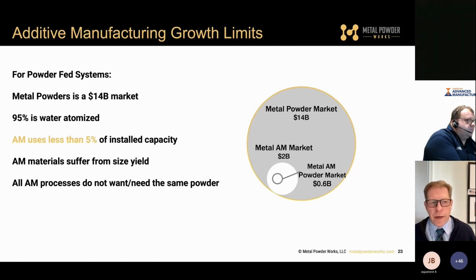95% of the metal powder market is water atomized. Currently, additive manufacturing uses 0% water atomized powder. So it means that we're only utilizing 5% of the installed capacity. At some point, this is going to restrict the growth of additive manufacturing if this were to continue. Most of the materials that are of interest to additive manufacturing are maybe different than what the metal powder market grew up with. So it's a lot of stainless steel. There's some Inconel 718 out there. There's some other materials, but we need to see more materials if additive manufacturing is going to really grow as everybody expects it. This is the problem, which is it's hard for it to grow when you get low yield out of the size fractions that's necessary for additive. So this is where perhaps we come in to fill part of this.